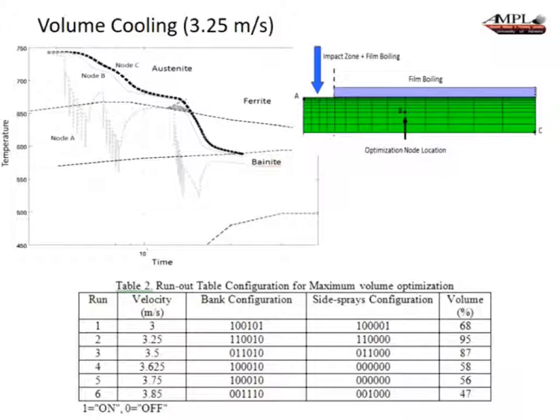So by doing that, I'll start with the table at the bottom here. You can see that looking at various velocities, what the configuration is of the banks and of the side sprays, and what the volume percent of the enthalpy that's retained appears to be. In this case, we were maximizing the enthalpy content of the strip. And so this particular run number 2 gave us the best configuration at 3.25 meters per second, with these configurations shown here. And that particular configuration is shown here through a schematic runout curve for node C, which is the one in the center line, node B, which is a quarter of the way in, and node A, which is on the surface. So that gives you an idea what kind of structure you might end up getting if you follow this particular path here.